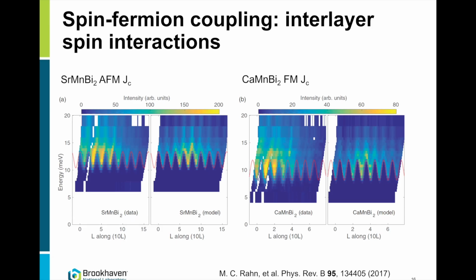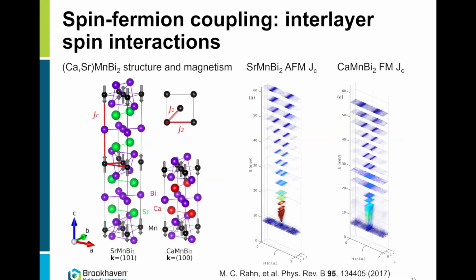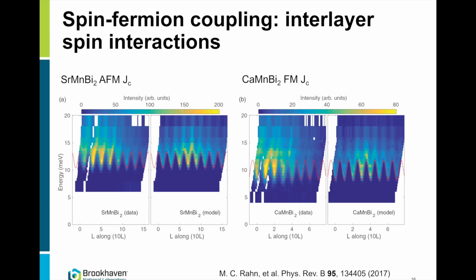So the dispersion in the interlayer direction is very weak. The coupling is small. The in-plane coupling is strong. So dispersion in the plane, it's very steep. But this dispersion in between the planes is weak. However, the bandwidth of this interplane dispersion determines the coupling, and its position of its minima. So for antiferromagnetic coupling, the position of the minima are at antiferromagnetic positions. Here it's 1 minus 1, and for ferromagnetic it's at 0, and so on.